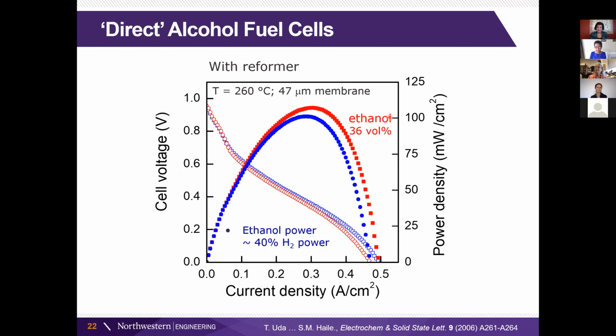That's great. And we said, well, how about ethanol? Because maybe you're sitting on the plane, you've run out of power, and what kind of fuel can you get? You can't actually get methanol, but you could get a little bit of ethanol. And that is also pretty good, not as good as the methanol, because ethanol is harder to break the CC bonds. And we said, well, let's compare that with the thing that you might actually get on the plane, which would be 80 proof vodka. And that works just about as well as our clean ethanol. So I like to say that's more demonstration of the impurity tolerance of our anode.